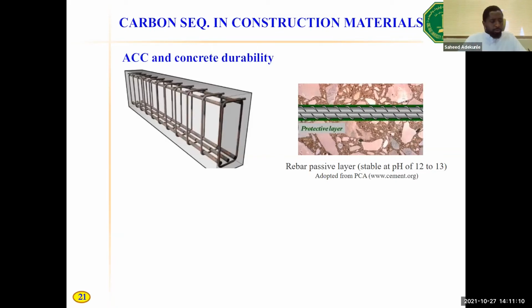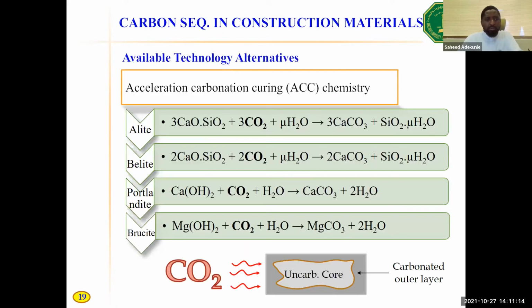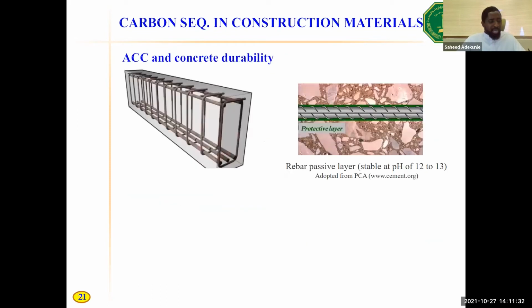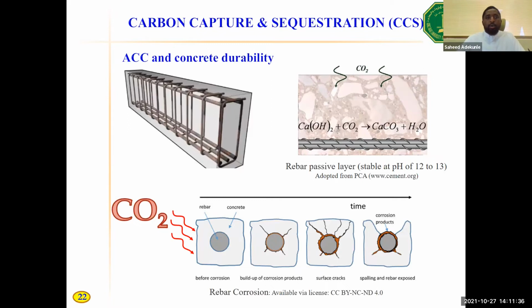But when you pump in CO2 in concrete, the outer layer, which has reacted with CO2, is acidic. It will de-alkalize the concrete and make it less alkaline. Less alkaline means the pH will reduce. Reduced pH means we lose the passive layer over the steel, and the loss of passive layer will result in a corrosion problem. And as you can see, if CO2 goes into concrete, the pH drops and corrosion could be triggered at an early stage, and the corrosion product will expand and cause cracks in the concrete. It looks like the ACC technology is not favorable to reinforced concrete members.